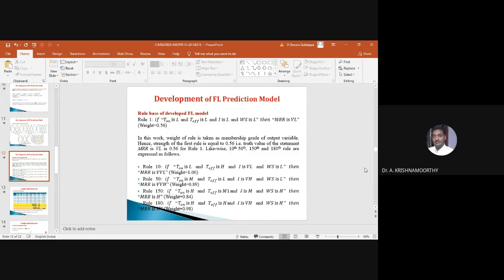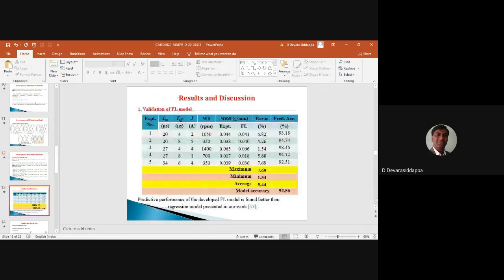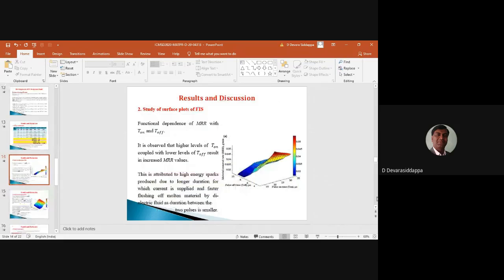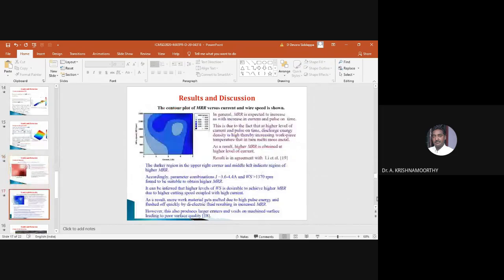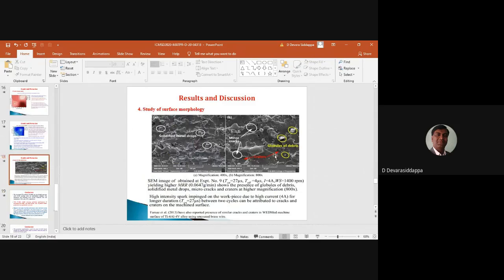Okay. Now you are concluding that with higher current and longer duration the surface also got damaged, right? There are some cracks and voids, cracks and craters on the machined surface. To avoid that, what do we have to do? Do you find this surface SEM image, a surface morphology presented at experiment number 9? Yes. And this gives you the highest value of MRR.